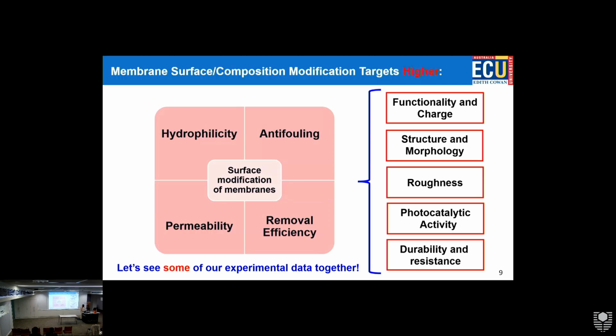How do we do that? We change the functionality or surface charge of the membranes. For example, in the case of micro and nanoplastics, majority of them are negatively charged. So if we increase the negative charge of the surface through polymerization or through integration of negatively charged materials on the surface, due to the electrostatic repulsion, they reject microplastics and other negatively charged contaminants. But this is something that we need to carefully consider, because if we have positively charged contaminants, it will enhance their fouling.